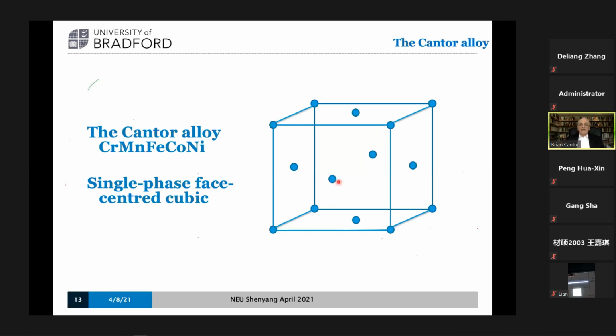But you do not expect to have 5 components in equal proportions on a single face-centered cubic lattice like this. That means that 1 in 5 of every atom at random is chromium, manganese, iron, cobalt, or nickel. And this is now called the Cantor alloy, and it was a big surprise. And in fact, there's a massive range of alloys around this particular composition. But let me continue with the story, because Alan did this work.